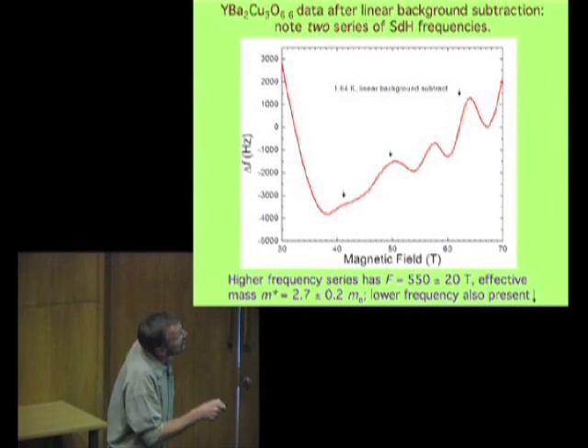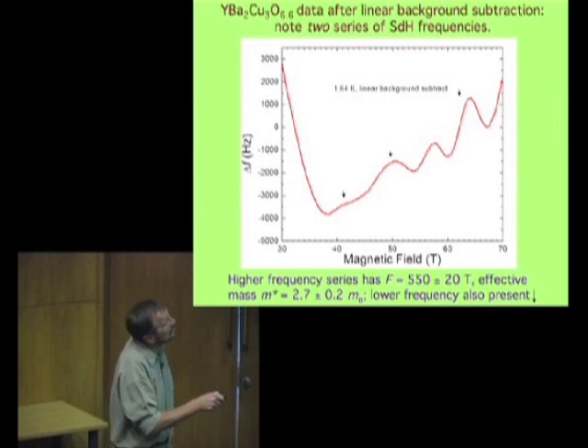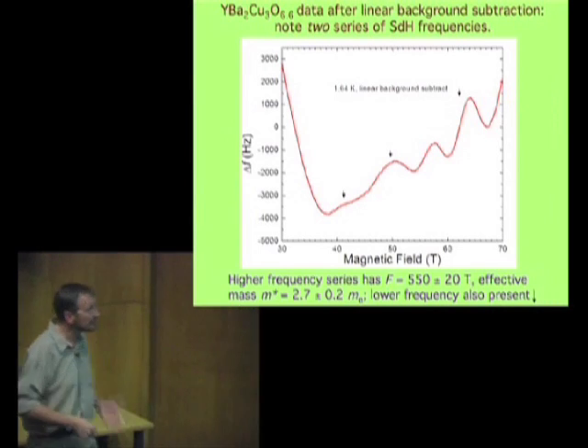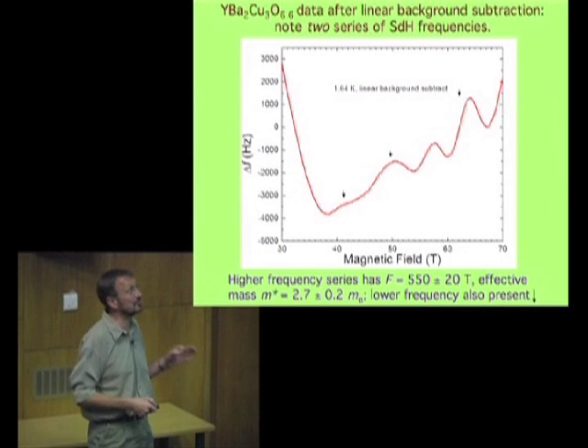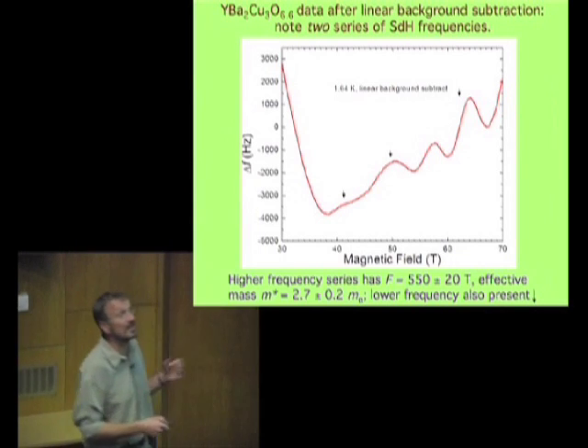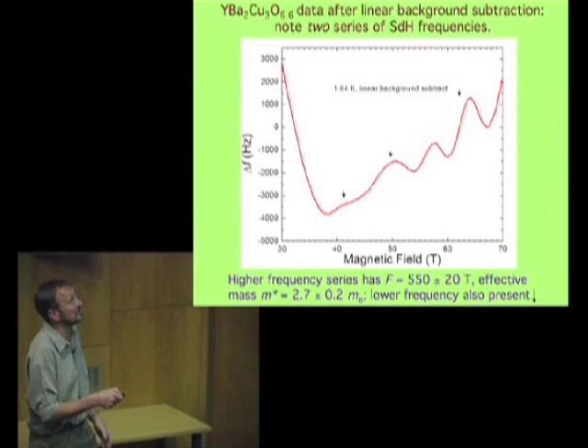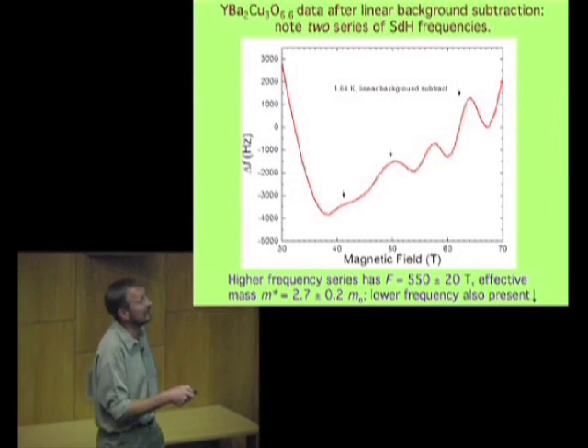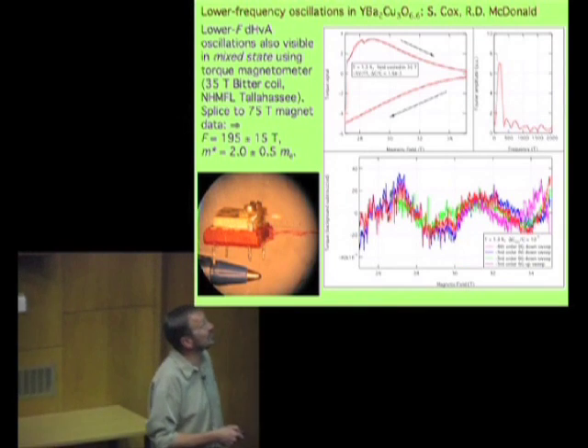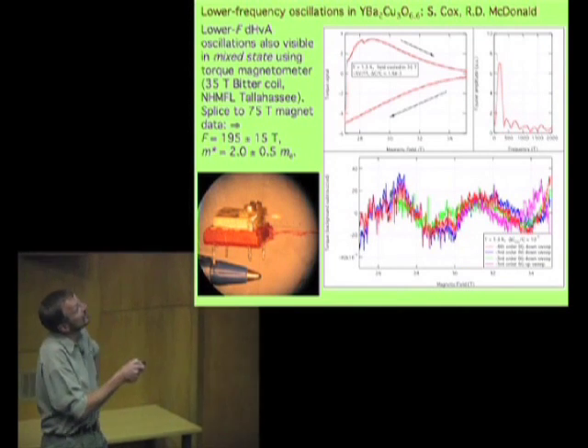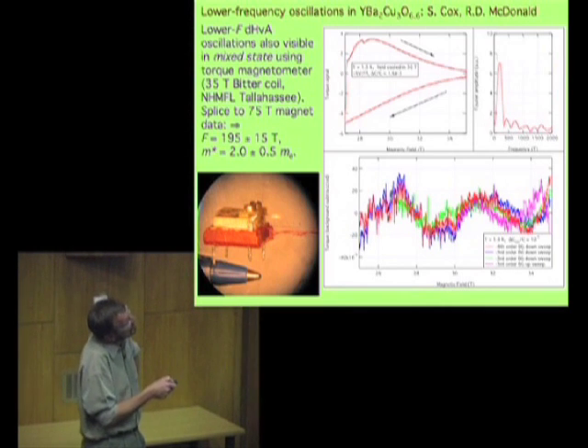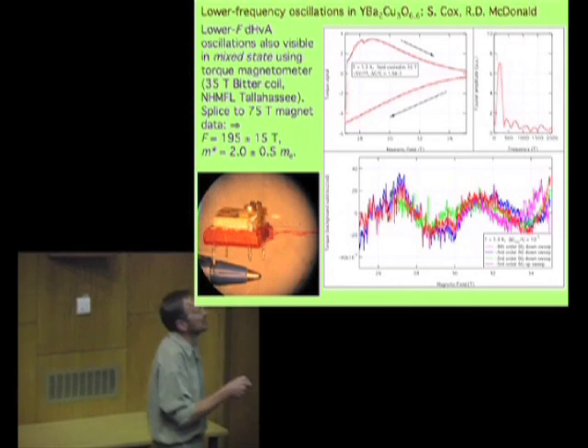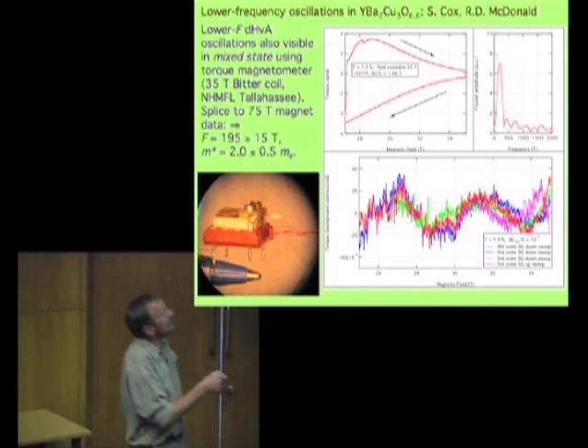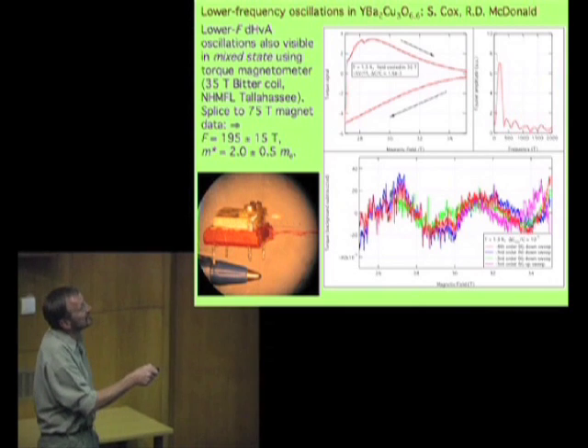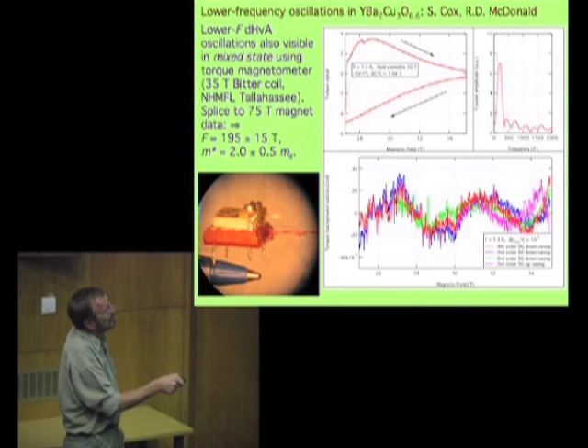Notice that there's the series which is about 500 Tesla in frequency here, and they're superimposed on a slower background frequency. Remember that every frequency you get corresponds to a cross-sectional area of the Fermi surface. So that means that the Fermi surface has 2 cross-sections, one of which is smaller and one of which is slightly larger. So to look for more evidence of that, we also went to the Tallahassee High Magnetic Field Laboratory and used a thing called a torque magnetometer to see if the oscillations were also present in the magnetization. This is basically like a little springboard made out of phosphor bronze with the sample on top of it. There's the sample. There's a Bic biro pen.